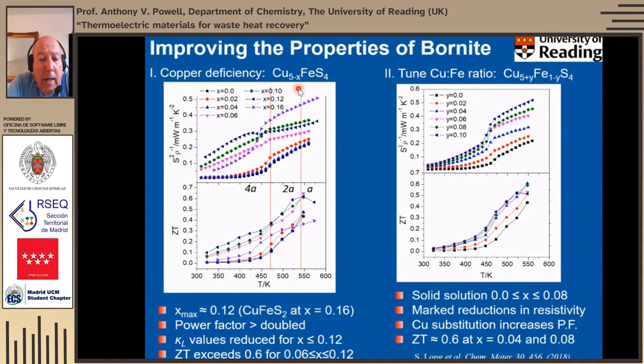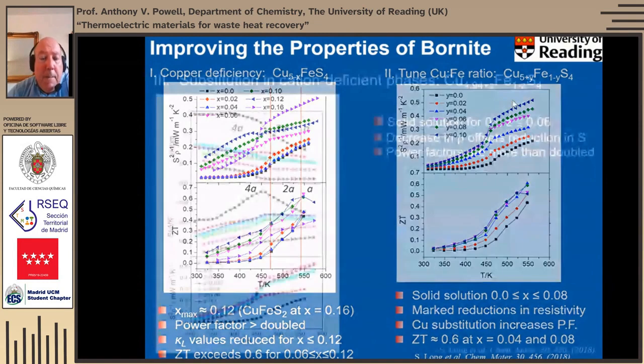We do get some significant improvement in the electrical properties. The power factor is more than doubled. The thermal conductivity is also slightly reduced, but the main impact is on the electrical properties, which is what we were targeting. And we can get a ZT that exceeds 0.6 in that material. We can get similar performance on a similar basis by just tuning that copper to iron ratio, which again results in oxidation of some of the copper. And once again, we can get to a ZT of about 0.6.